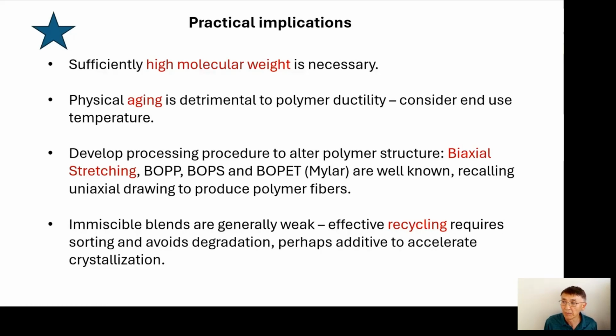It really summarizes all the known practice that we have today. In particular, I think it takes my theory to properly understand the effect of biaxial stretching. So, this process is industrially widely known. The reason they do it is to alter the structure in favor of achieving ductility. And of course, it even talks about, we can also understand why typically immiscible blends suffer weakness because of incompatibility disrupting the network.